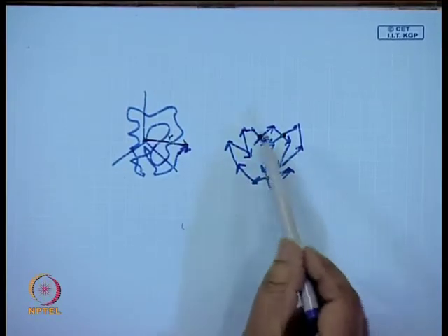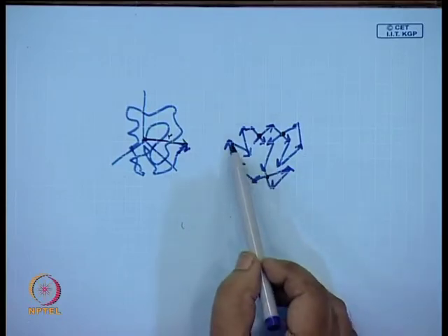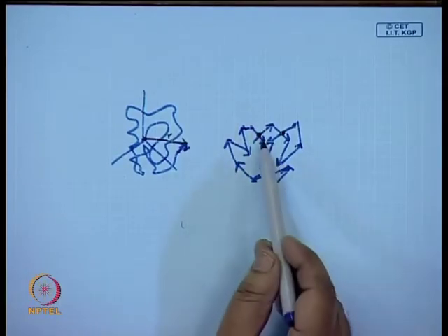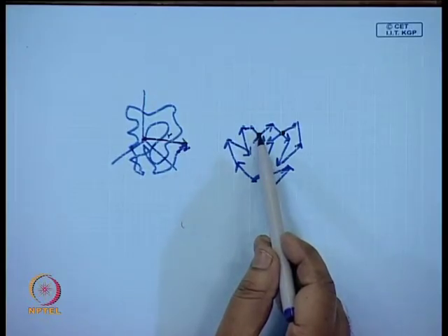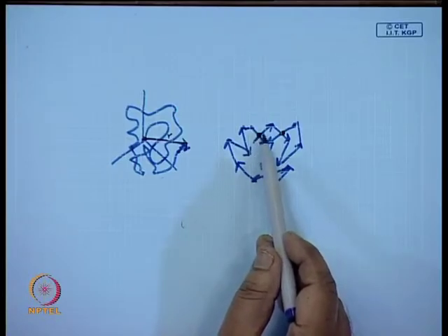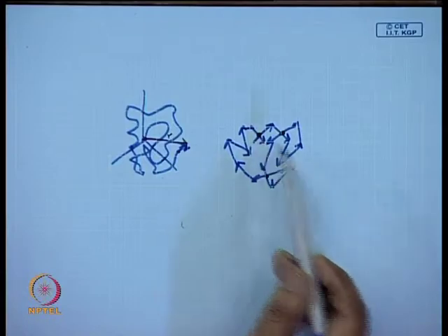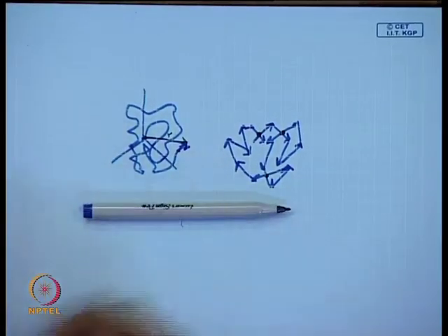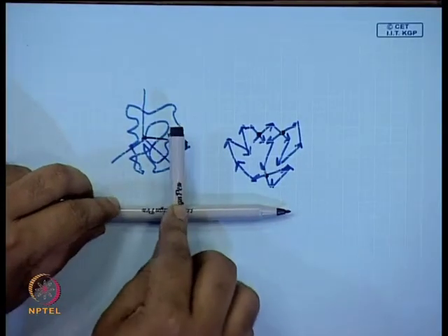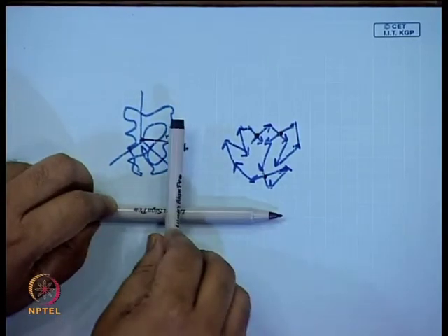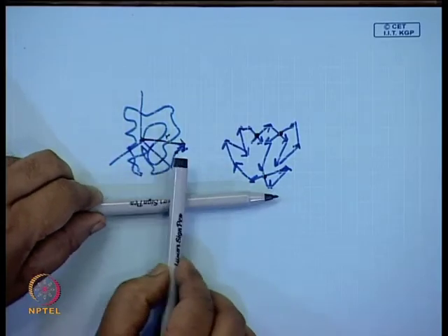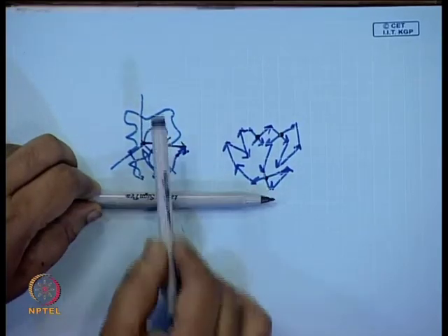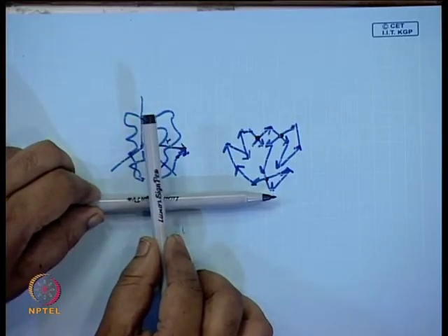So, now when we deduced this expression, we did not consider that these vectors have volume. So, what happened? In this model, we considered that the same space, at the intersection points, can be occupied by two bonds. But in actual sense, if you have one bond, what I was doing in the model was basically putting another on top of it, on the same paper itself, and calculating the dimension. But in actual terms, because this has a definite volume, you cannot put it on the same paper, these two cannot intersect on the plane of the paper. It has to expand, because this has volume.